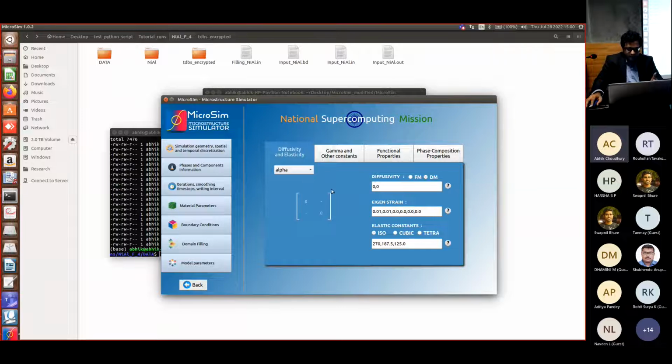Now you see in the diffusivity matrix there are two components. So you need to give two entries, and I'm giving alpha. This is a solid, so there is no diffusivity. In the liquid, I have 1.9 and 0.5 E minus 9. So they are not equal diffusivities, they are unequal diffusivities in the diffusivity matrix, right? So there are k minus 1 cross k minus 1 independent diffusivity matrices. I'm just giving a diagonal matrix over here, so only these are populated. All right.